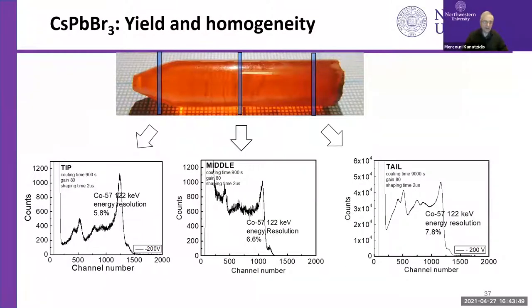Here's an example. We made an even bigger crystal, close to just under an inch. This is the response that we got from three different parts of the ingot. As you see here, in all cases, we do resolve the cobalt-57, 122 keV spectrum with good resolution. Here's 5.8, 6.6, 7.8. These are planar detectors we made. So this is quite promising material, actually,